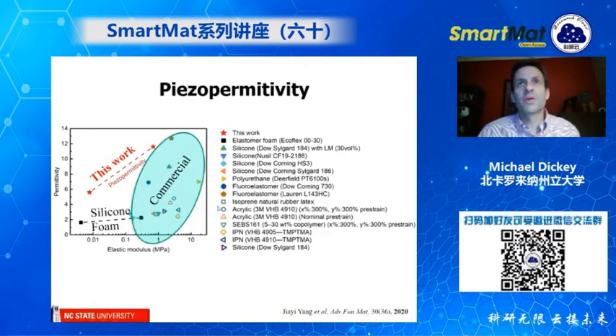So the exciting thing from this work is that if you take all the commercial elastomers and you plot them versus the modulus and the permittivity, you can see that most commercial elastomers fall over here, which means they have a relatively high modulus for silicones, and the permittivity kind of spans these values. In our case, we can make a silicone foam, but unlike regular silicone foams, we can make it much higher dielectric constant by adding the liquid metal.